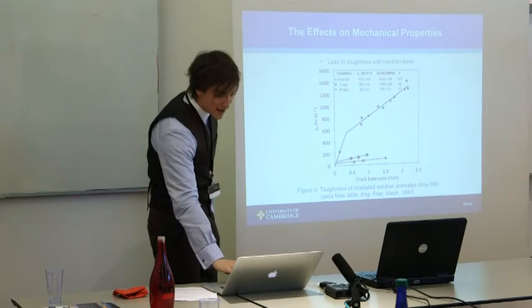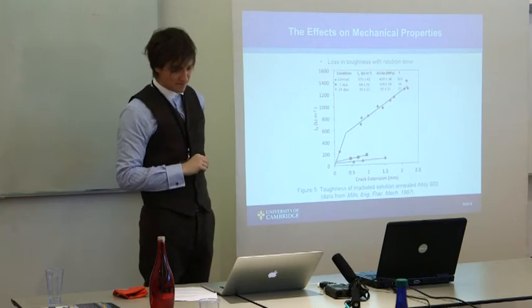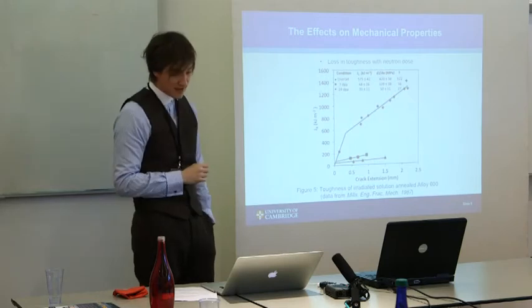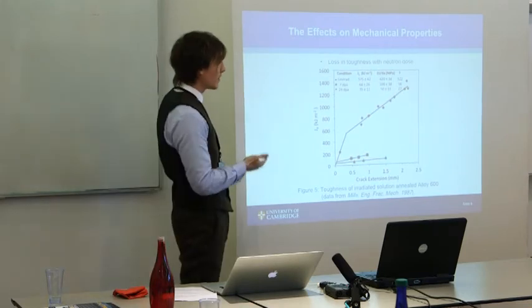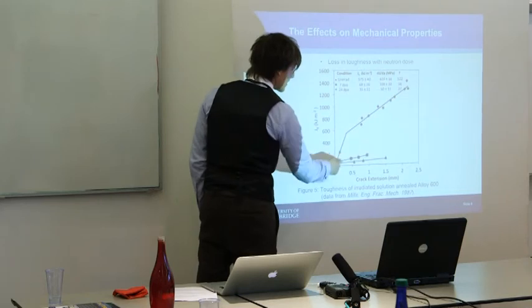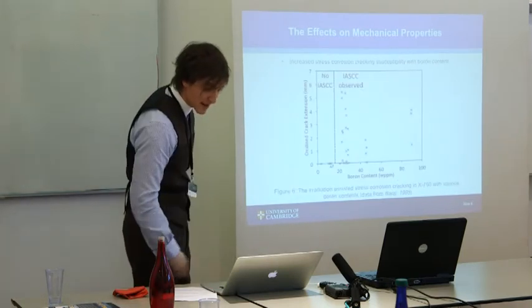Not only that, but you get a loss in toughness. Toughness on the y-axis versus observed extension of cracks on the x-axis shows that you require less energy to propagate a crack when the material has been irradiated. Going from non-irradiated to 7 DPA to 24 DPA, increasing dose means the material just cracks much more easily.